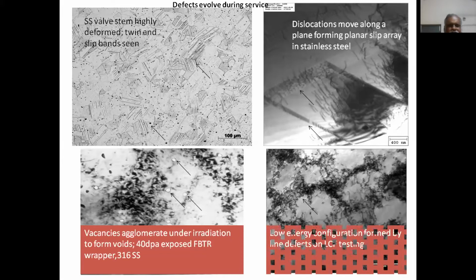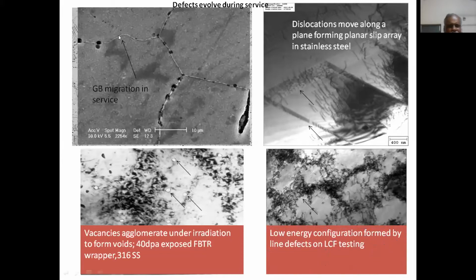This is a classic example of grain boundary migration, which has happened in a creep exposed sample. What Dr. Matthew was speaking about, this is a sample which has served for 30 years in the reactor environment. When it came to me for a failure analysis, I could see a number of precipitates around the grain boundary. You could see the triple point, with several precipitates. The grain boundary has actually migrated here. This is due to creep. Okay, so all these things you can understand if you have a very good eye for microstructure.